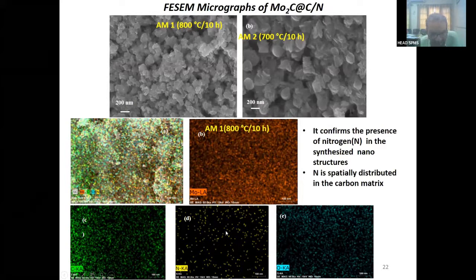So we have taken independent X-ray dot mapping of our material which has been synthesized at different temperatures. The important part I want to illustrate is the content of the molybdenum, which is highly dense, you can see in the B microstructure, and then carbon, which is also dense here in the C, and in the D part nitrogen. Nitrogen is not so dense, but it is uniformly distributed. It means that our material is highly homogeneous in terms of predicting the property. It will give rise to isotropic property, not anisotropic property. Okay.